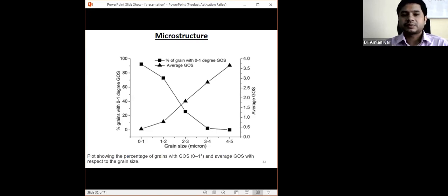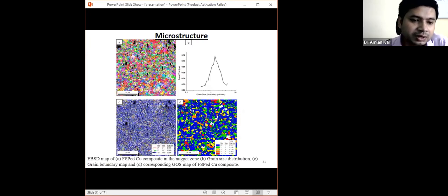sub-grains or the sub-grain boundary. That means the grain boundary corresponding to blue and green is accumulating the dislocation density, and because of the accumulation of the dislocation density, the orientation deviation across the grains increases. Because of the increase in the orientation deviation, this grain boundary is converted from a low angle grain boundary to a high angle grain boundary. In this process, the single grain is refined further into smaller grains, and therefore we get a refined microstructure which has been observed here.